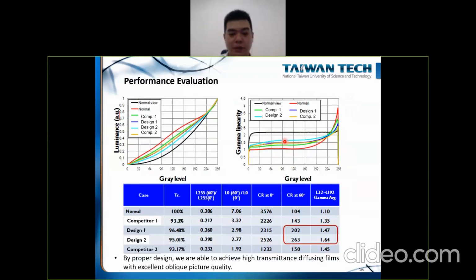So this is based on the simulation. Okay, so this is based on the experiment. We actually contacted our supplier to make the film based on our simulation, and then we put the film on top of our display, and you can see the transmittance. We have two different designs. You can see that the transmittance dropped by about 3 to 4%, and the contrast ratio at large angle can be improved from 100 to over 200 for the actual film.